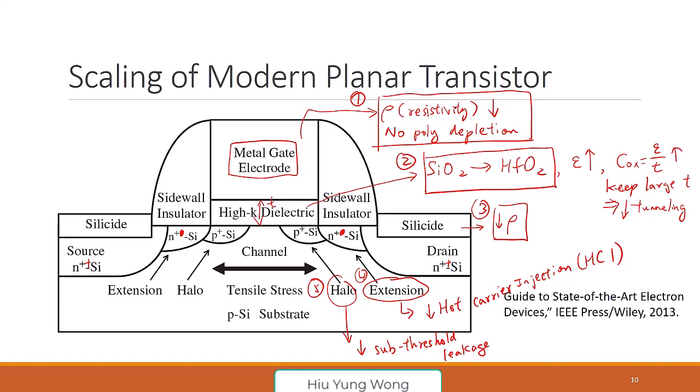But now technology is so good, they can adjust the work function of the metal gate. And if you look into the papers by them, you see they actually use multiple layers. Sometimes they use multiple, very thin layers of metal to adjust the effective work function. So this work function is soft. And also they have good conductivity.